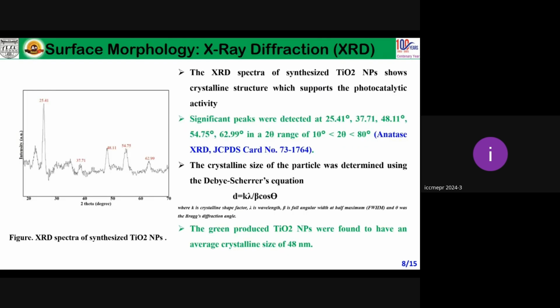So now, to ensure that the particle formed is TiO2 or not, XRD analysis was carried out, and different peaks were obtained at two theta values of 25, 37, 48.1, 54, and 62.99 degrees. When it was compared with the standard JCPDS card number 73-1764, it resembles the peaks of the anatase phase of TiO2 nanoparticle, and the particle size, calculated using the Debye-Scherrer equation, was around 48 nanometers.